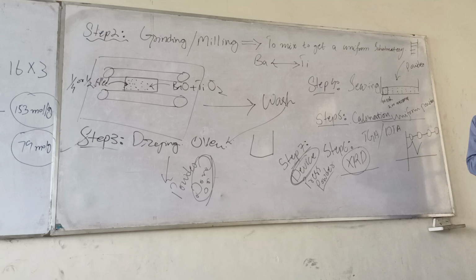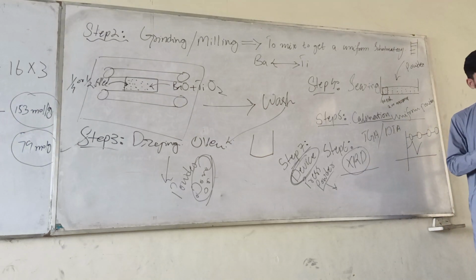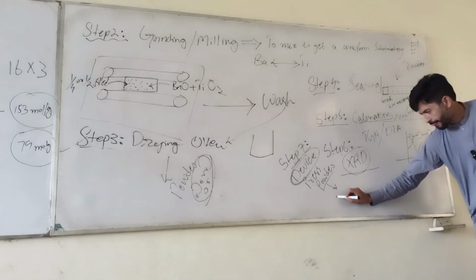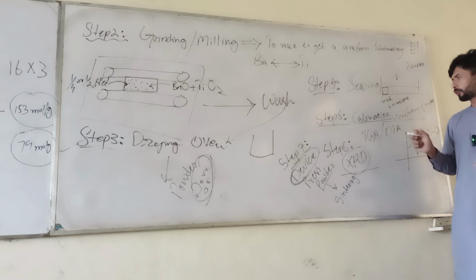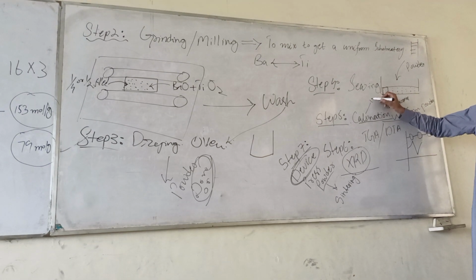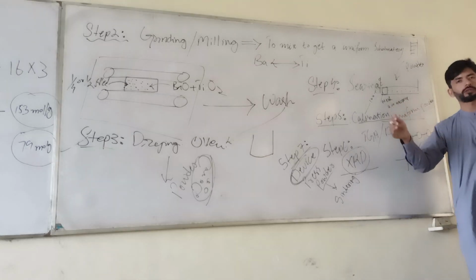But those tablets, when you see, are not properly adhesive to each other. It still has very low mechanical strength. Yes, sir. It can be easily broken. Yes, sir. So for that purpose, what you will need is to sinter that pellet. Sintering, so that they become harder. So what is the required sintering temperature? This is 100 or 150 degrees above the calcination temperature.